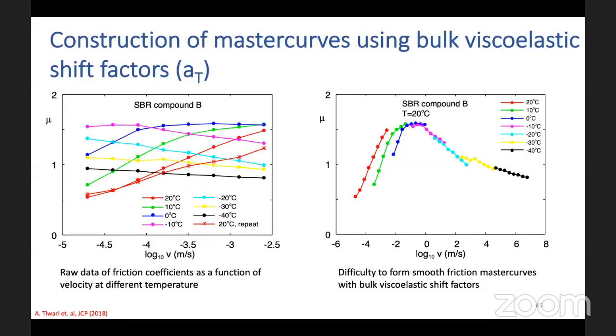So what we did in Jülich is we wanted to see if we can do the same sort of experiment that Grosch did in 1963 with the current technology. So we repeated this. We took a rubber compound, and we did the same thing. We measured friction coefficient at different temperatures as a function of velocity. We measured from 20 degrees Celsius till minus 40 degrees Celsius, and we got these curves.